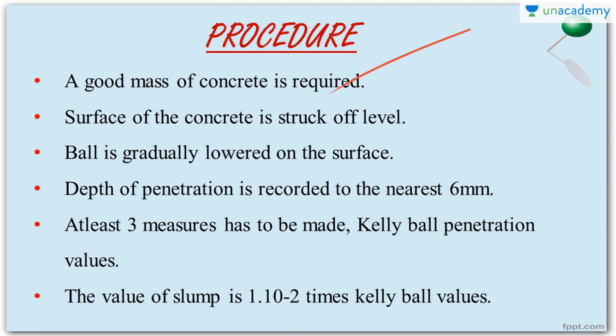Take the apparatus and hold it just above the concrete surface. Allow the ball to gradually lower into the concrete matrix — it has to be driven down by gravity only; no push should be given. Once the sinking is complete, the depth of penetration is recorded to the nearest 6 mm from the graduated stem. At least three measurements must be taken. These measurements are known as the Kelly Ball penetration values.